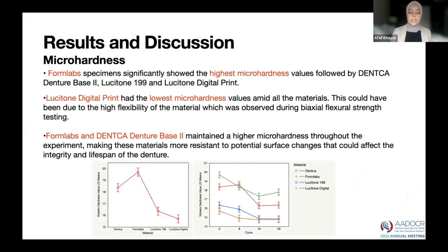For micro hardness, Formlabs specimens significantly showed the highest micro hardness values, followed by DENTCA Denture Base II, Lucitone 199, and Lucitone digital print. Lucitone digital print had the lowest micro hardness values amid all the materials. This could have been due to the high flexibility of the material, which was observed during biaxial flexural strength testing. Formlabs and DENTCA Denture Base II maintained a higher micro hardness throughout the experiment, making these materials more resistant to potential surface changes that could affect the integrity and lifespan of the denture.